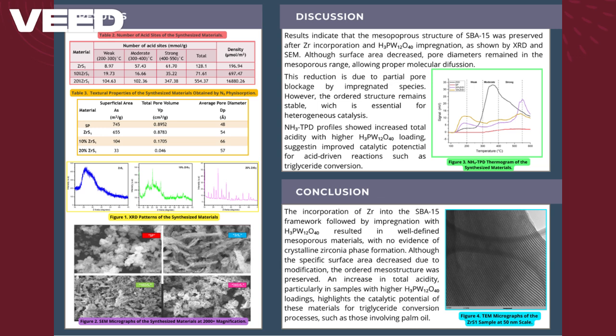Wide-angle XRD patterns, Figure 1, show that Zr-1 displays a broad peak around 25 degrees, characteristic of amorphous SBA-15, with good Zr dispersion and no crystalline zirconium oxide, favoring porosity. 10% Zr-1 shows additional sharp peaks, attributed to partial crystallization of phosphotungstic acid, enhancing acidic sites without compromising the SBA-15 mesostructure. 20% Zr-1 exhibits more intense and defined peaks, indicating higher crystallinity and greater active acid phase within SBA-15 while maintaining porosity and dispersion.